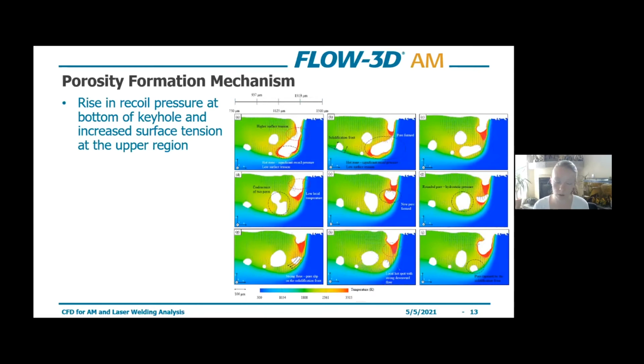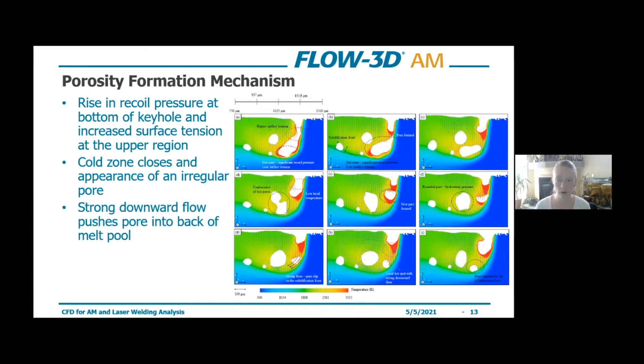Once we transition into keyhole mode, you'll see a large keyhole opens up, and there's higher recoil pressure at the bottom of the keyhole, because that's where most of the heat is concentrated. And because of the higher temperature at the bottom of the keyhole, we're going to end up with lower surface tension pressure. Conversely, at the top of the keyhole, you have higher surface tension pressure. This can form a cold zone, which can lead to momentary keyhole collapse, which is what leads to the initial pore that gets trapped in the melt pool. Once that pore gets pushed backwards from the strong downward flow in the molten pool, it'll round off due to hydrostatic pressure. It may be released at the top due to buoyant forces, but in some cases it's trapped by the advancing solidification front, and that's what leads to the porosity in the final part.